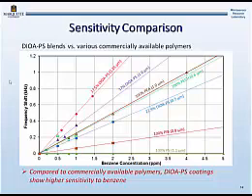This mixing ratio is 22.9%, thickness 0.7 micrometer. And this gave us stability for over 3 months. So we can see that compared to commercially available polymers, the polymer plasticizer coatings show higher sensitivity and are good additions to a sensor array.